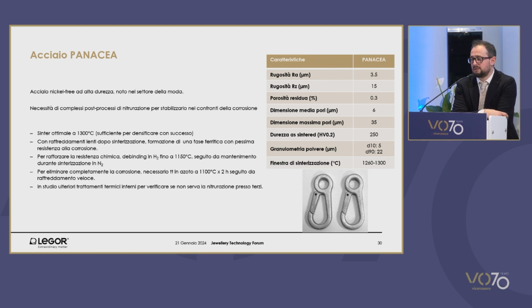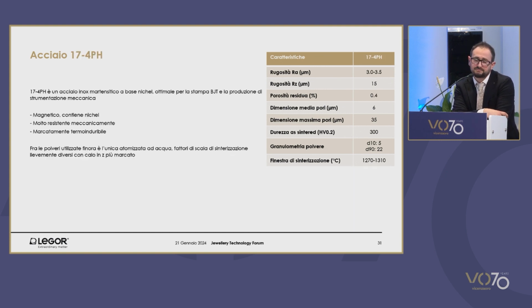The sintered item can be treated to sort out the problem of corrosion, 1,100 degrees for 2 hours in nitrogen. But of course, this is costly because it has to be carried out in other companies. So we're now working on a treatment that then can take place during the sintering phase through the insufflation of nitrogen. And this has already significantly reduced the problem, although we cannot say that the result is excellent yet.